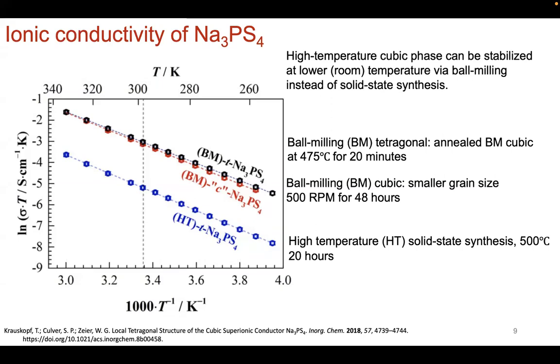So what you see, loosely, is the natural log of ion conductivity times temperature. The activation energies are pretty similar, but the ion conductivity is increased when you go from the tetragonal phase to the ball mill cubic phase. That's achievable at lower temperatures. And then when you anneal it to get to the tetragonal phase again from the ball milling, there's some deviation, but for the most part, they're similar.